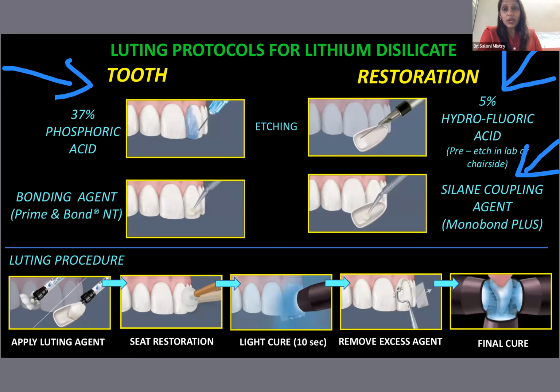Then you apply your bonding agent depending on the system that you're using. If you're using a light cured system or a dual cured system, accordingly it will change. Let's just take it up as a dual cured system. When you're using a dual cured system, you mix your Prime and Bond NT: one drop of your Prime and Bond primer and one drop of your adhesive. Mix it and apply it onto your tooth surface, as you can see in this, and light cure it.